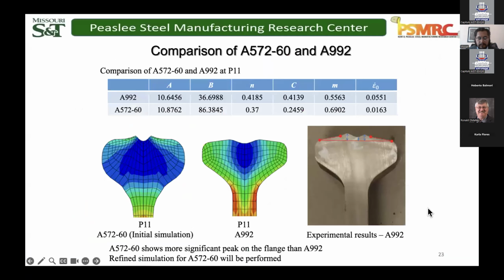And then we develop the constitutive equations that feed into the appropriate forming models using finite element to actually track the evolution of shape and defects in product. And we've had great success mimicking industrial processing. This happens to be a beam rolling at Nucor Yamato, where we were able to successfully predict the defects formation associated with one grade of steel that has different flow characteristics than a traditional A992 steel.